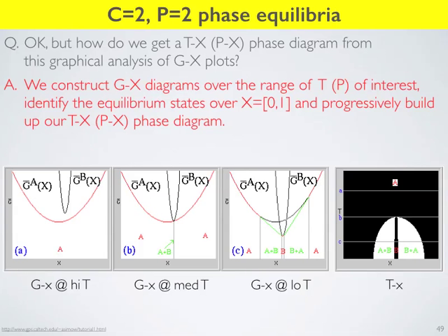So by plotting these Gibbs curves at different temperatures, analyzing the behavior, and plotting these section by section buildup of the phase diagram, we can construct these phase diagrams that we're very used to seeing in textbooks and in journal papers. So you may not have worried too much about where these things came from before, but this is one way, computationally, of constructing them. And so, of course, we don't have to go through this laborious graphical procedure. It's all done numerically by the CALPHAD software. But in principle, this is really what's happening.